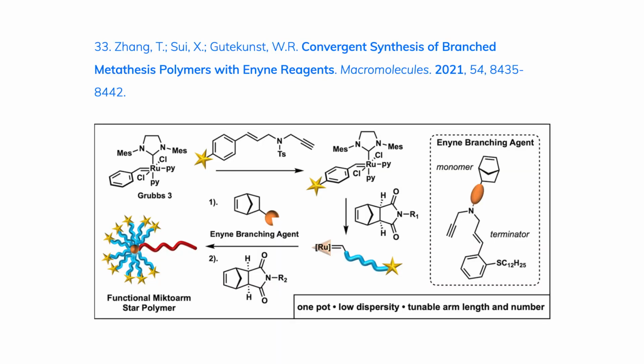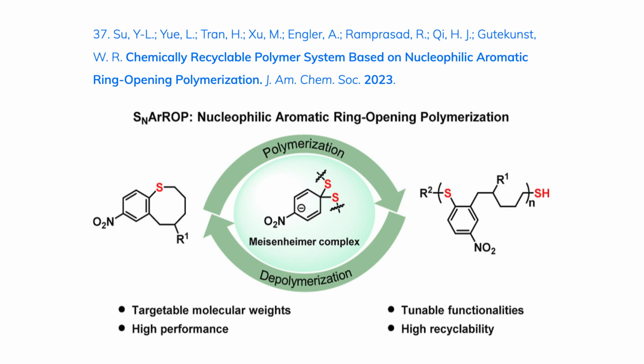In another venue, we're trying to develop entirely new types of materials. So these are monomers, and you can polymerize them, make a polymer, it can do its job, and then on demand, it will depolymerize and go all the way back to the monomer we originally started with. This is a really effective strategy because whenever you normally take a plastic and go through the mechanical recycling process, you erode its material properties. It's not as good the second time you use it as the first time. With this, we're going all the way back to the original monomer. This means we can completely resynthesize the material.